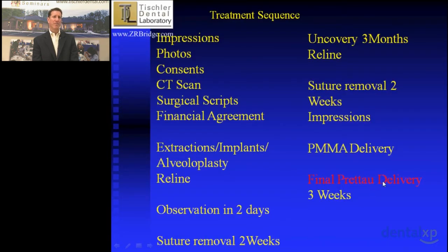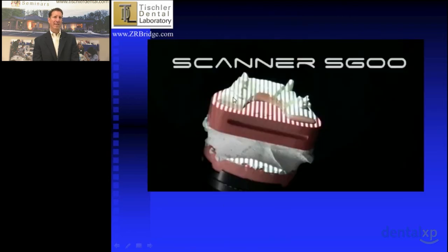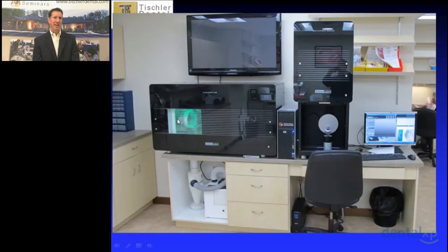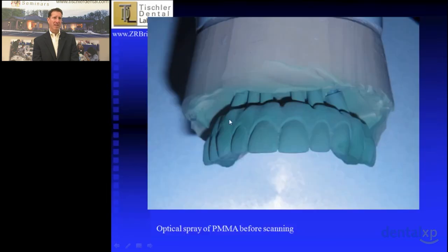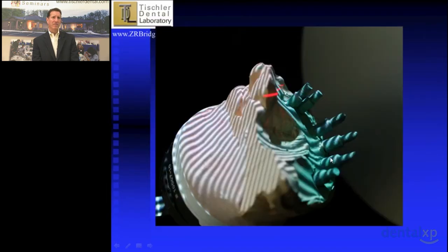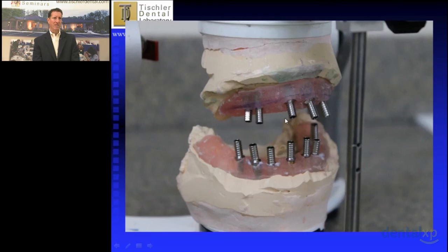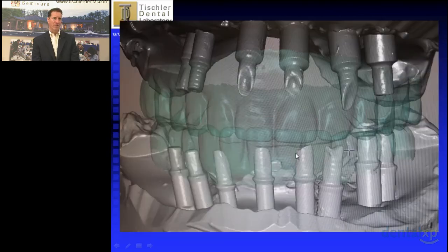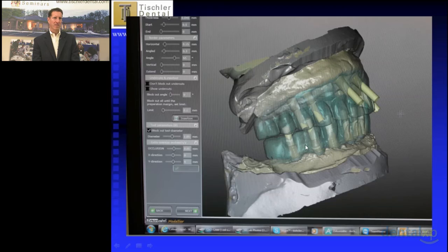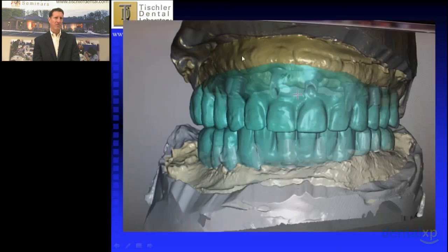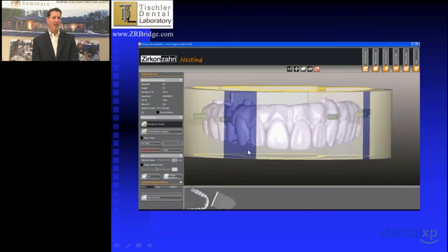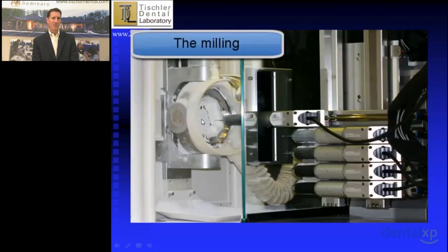And what we do is we take that PMMA and we scan it. And what we do is we marry that with the interface positions in the software. This is the Zirkonzahn scanner, and this is the Zirkonzahn milling machine. And we take this design, and we actually design it, and then we mill out a zirconia version of the acrylic temporary. You can see all the CAD-CAM designing we do here. And now we then virtually place that into the zirconia puck, and the milling machine now mills that out.